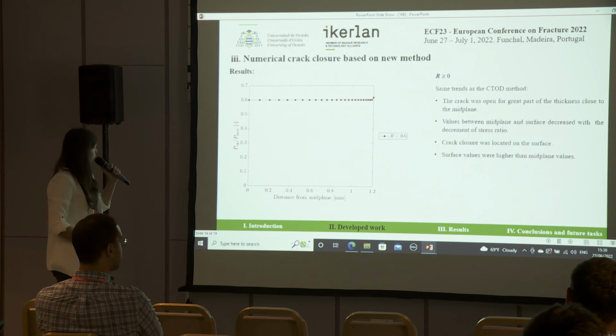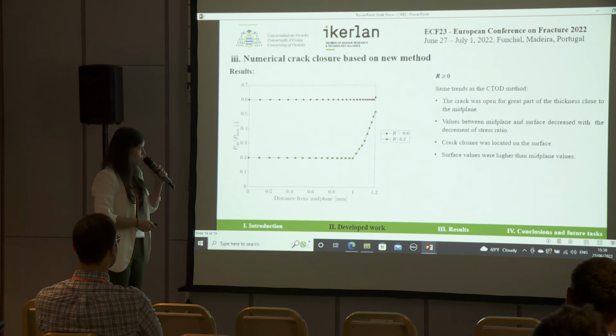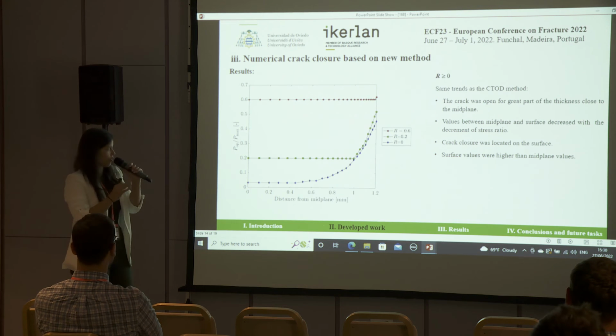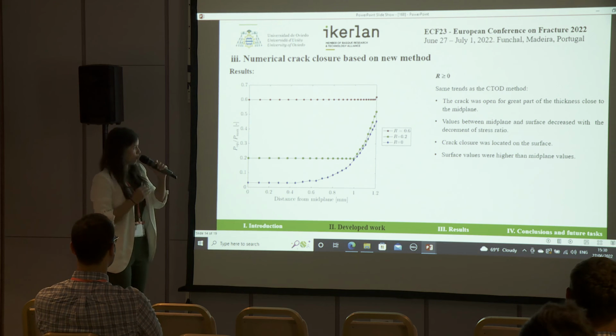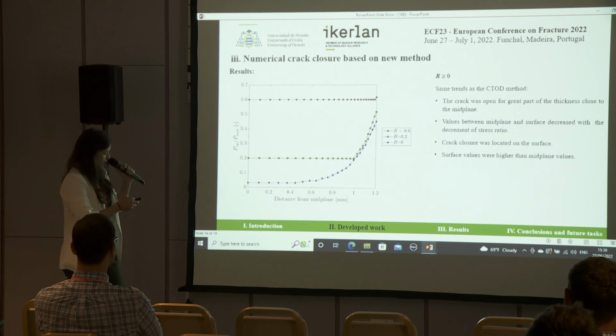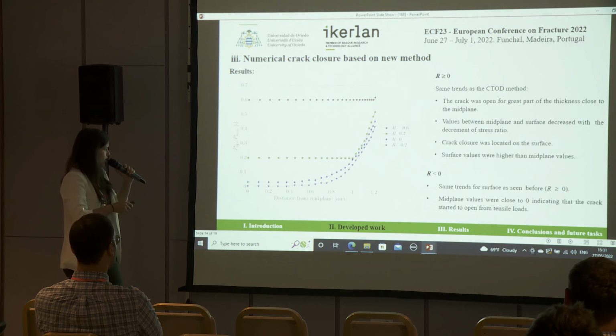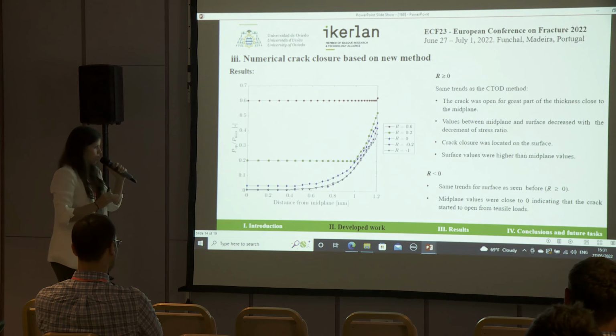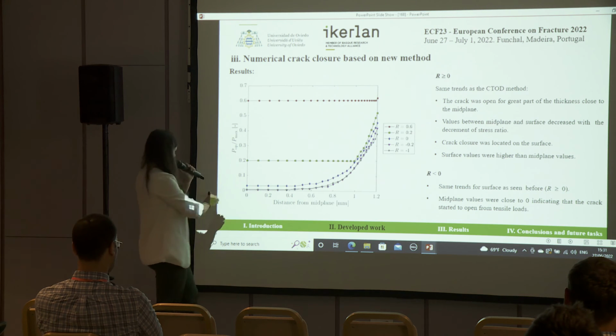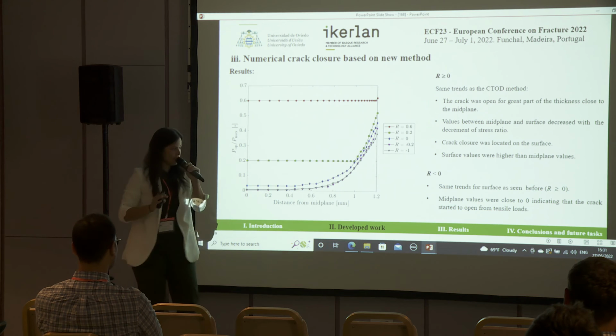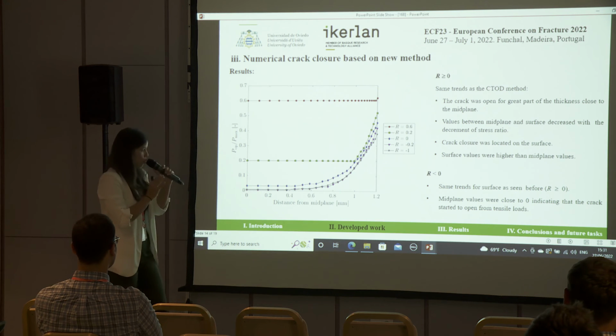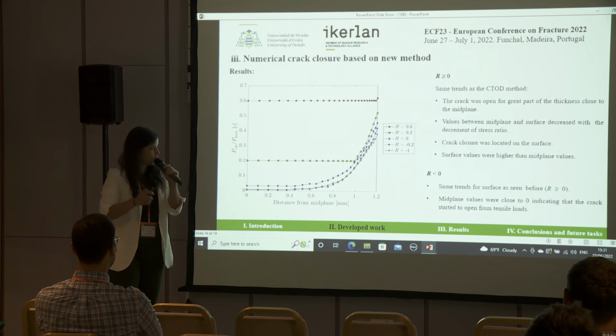So following again with the results, focusing on the negative stress ratios, the same trends as those obtained with the CTOD method were identified. However, in this case, the midplane values were close to 0, indicating that the crack started to open from tensile loads.